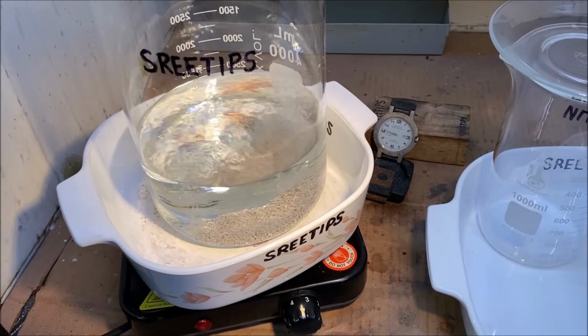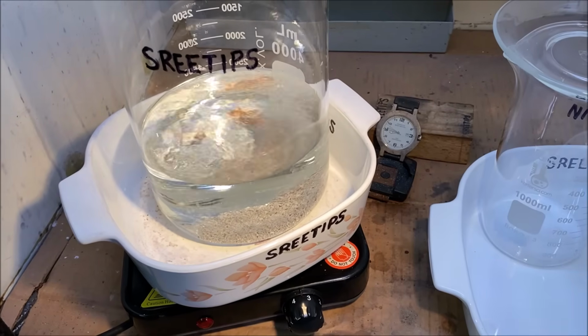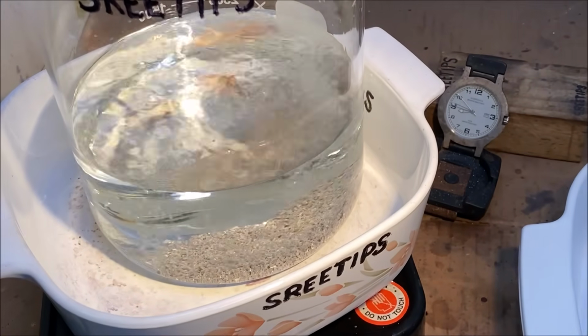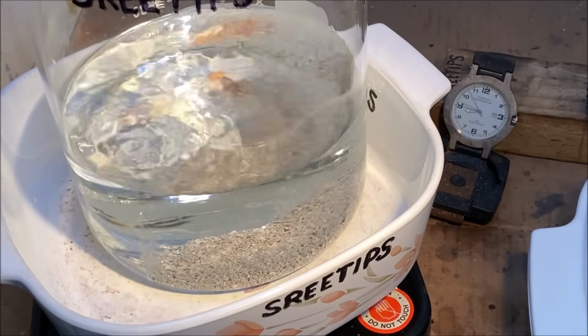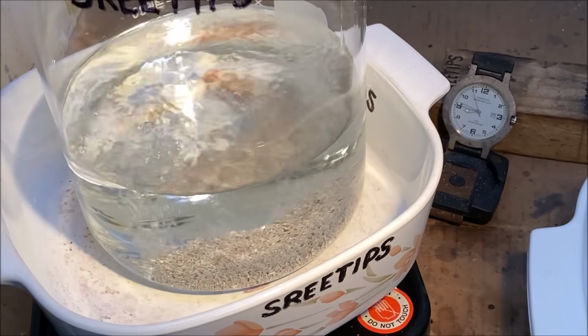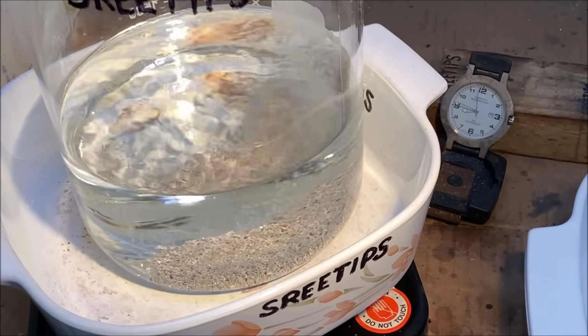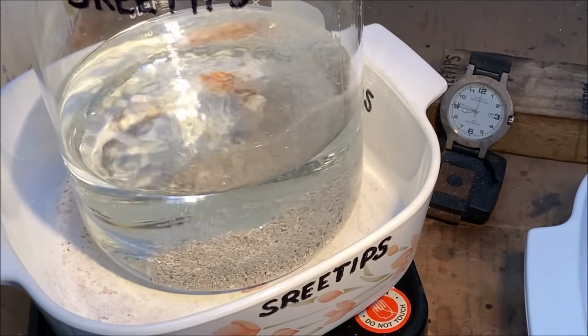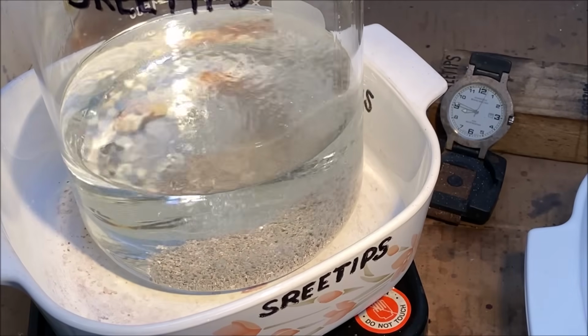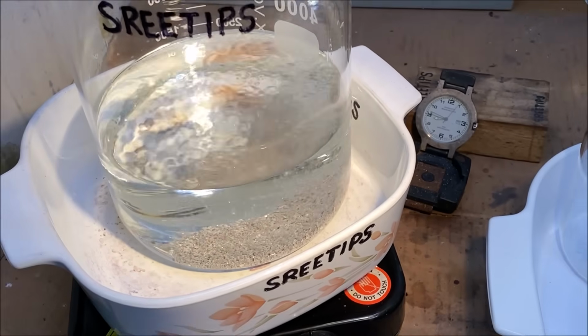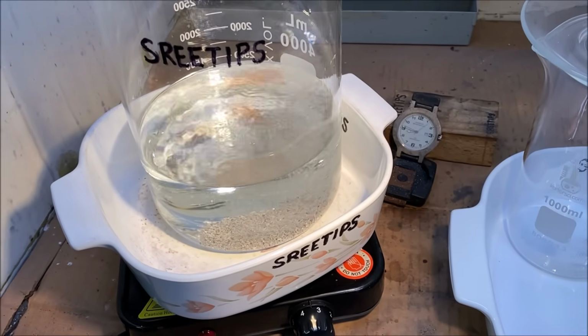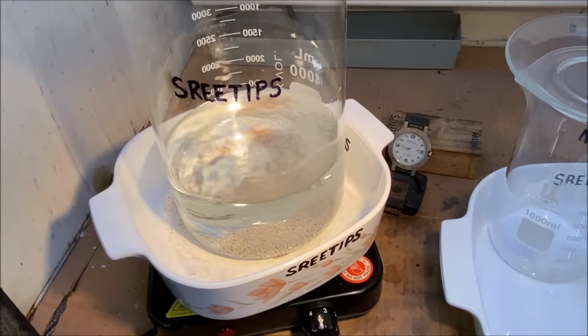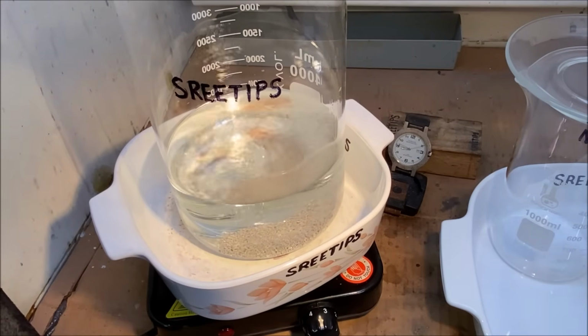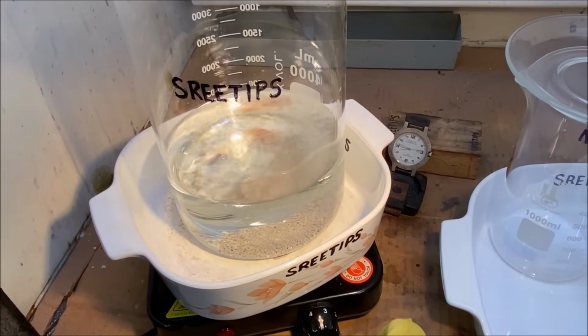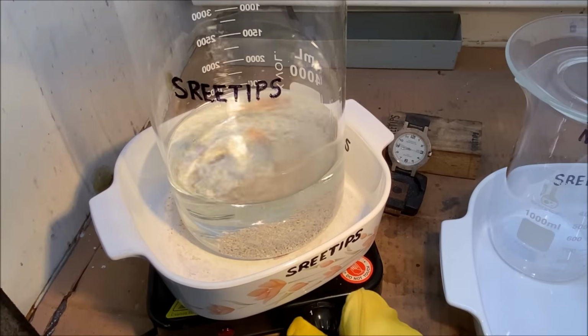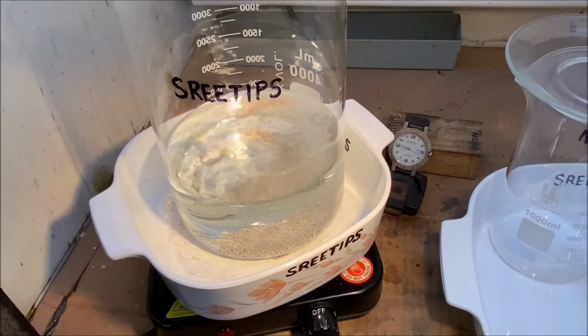I've allowed this to simmer overnight to ensure that we've got all the nitric out of our solution. As you can see, it's got a nice boil going on, no fumes, and just a little bit of silver left down in the bottom of the beaker. That ensures that we've got all the free nitric expelled from that solution, consumed out of there. So I'm going to turn this off now and let it cool down.